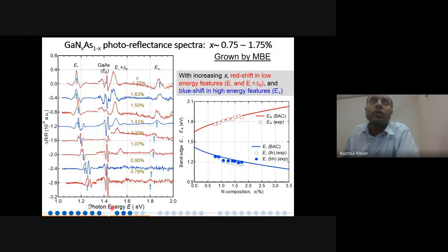So this is what we call photoreflectance spectra, and I told you that gallium arsenide has a band gap of 1.42 electron volt, and this signal is coming from the photoreflectance. This signal is coming from your substrate, so this is a reference. But from your material, the thin film on top of the substrate, we have a low band gap material. If you go down and down, this is the photon energy, but it also tells that this is the band gap. These all tell your band gap. Whatever feature you see tells that we do have a band gap.